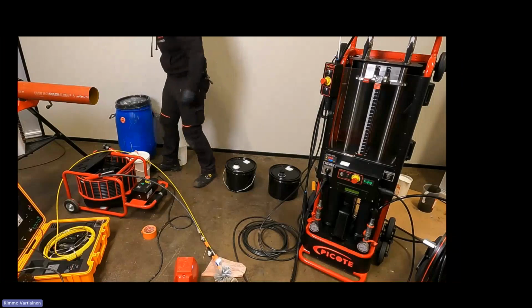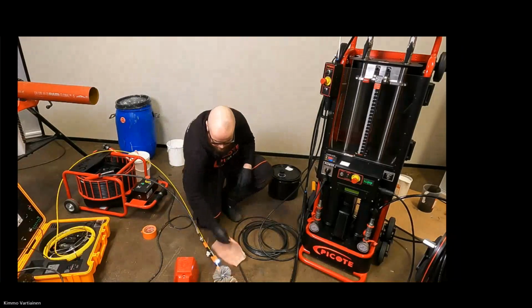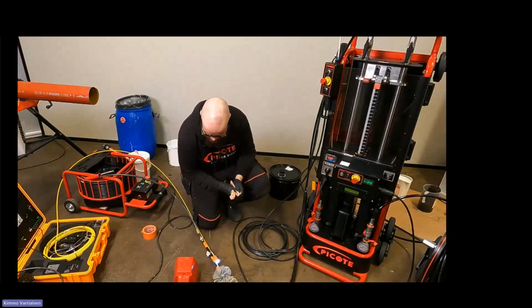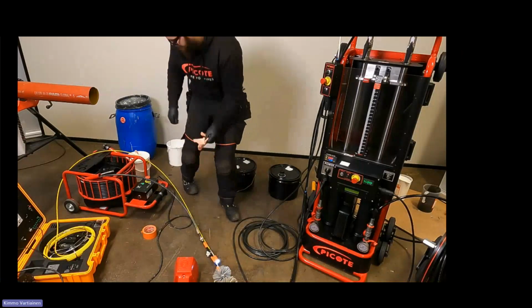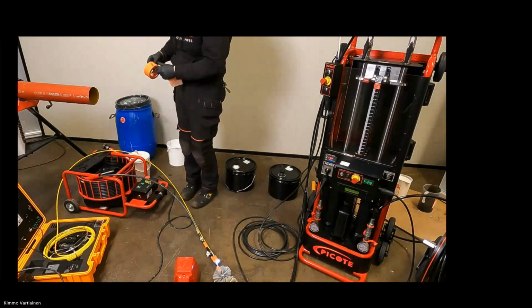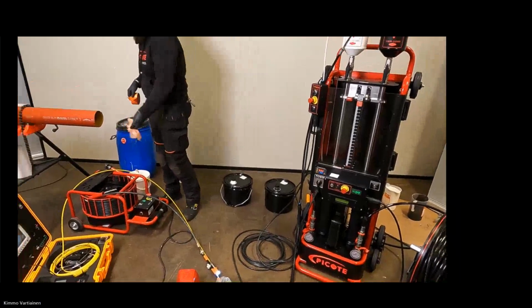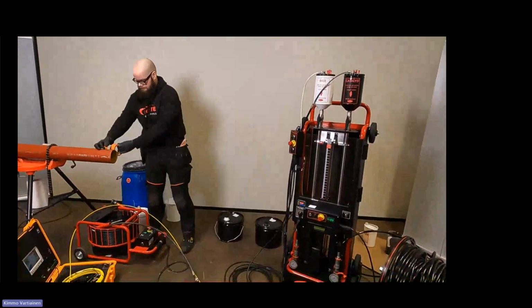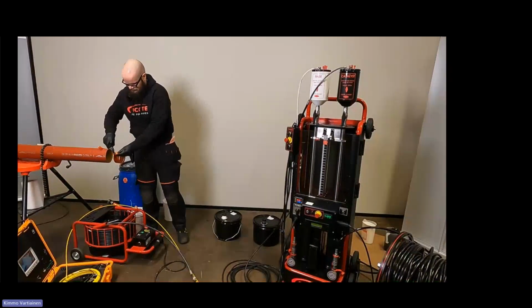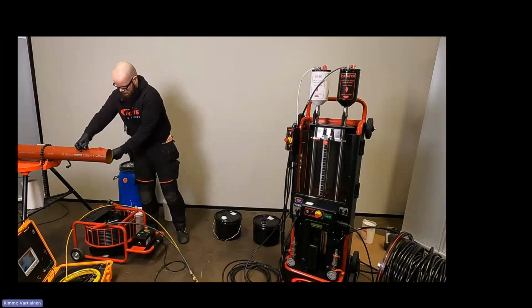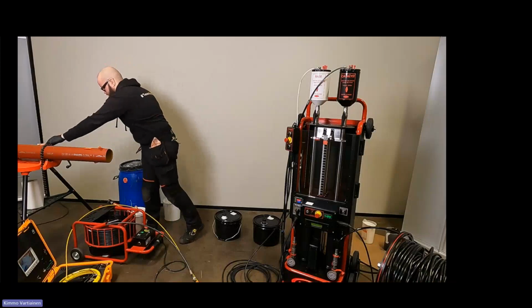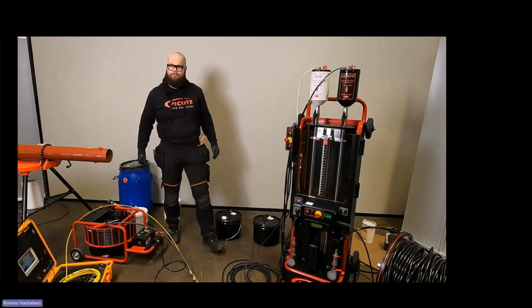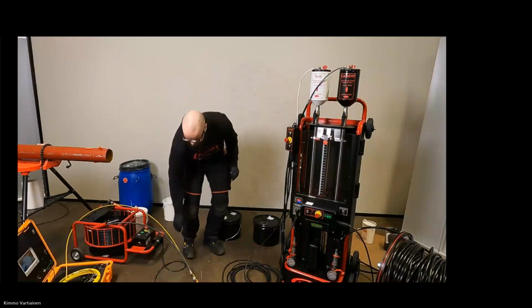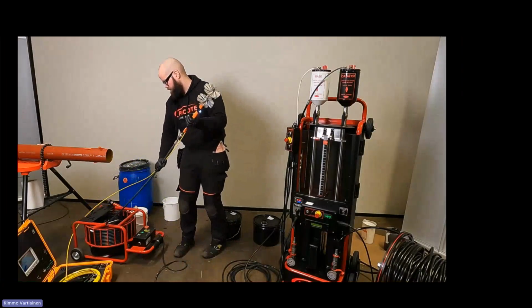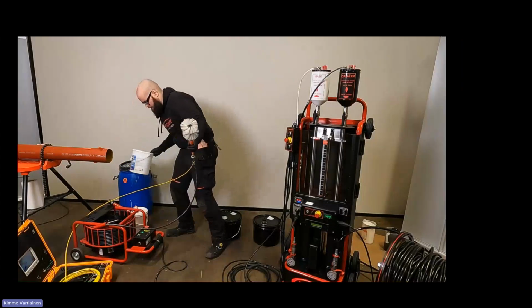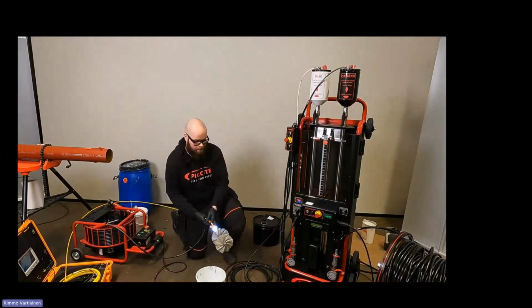Kimo's talked about the hose reel, and it's got a drive system on there. We only use the drive to run the hoses back onto the drum once we finish coating. Whilst we're coating, the operator, you'll see Kimo, will be slowly pulling the brushes back through the pipe. And what he's looking for with the CCTV camera is that we have a ring of liquid resin on the tips of the brushes. And if you pull back at the right speed and you watch with the camera, we should finish with a coating thickness of 1 millimeter.